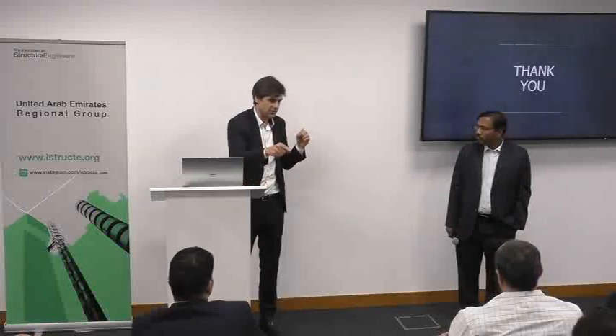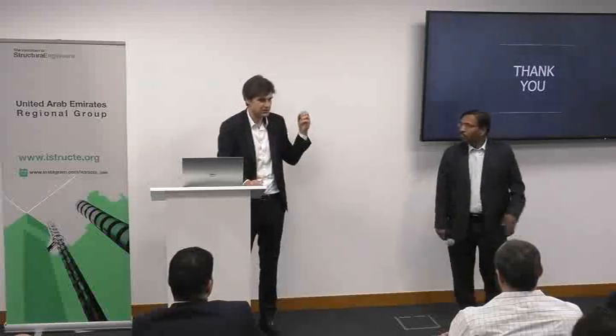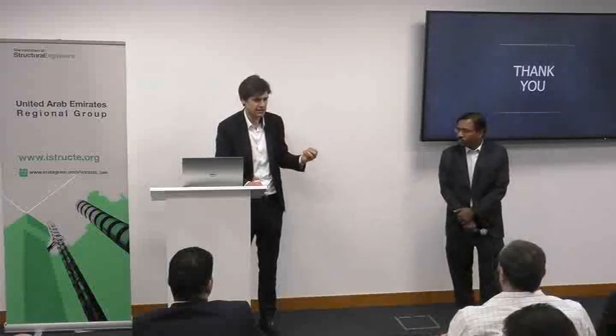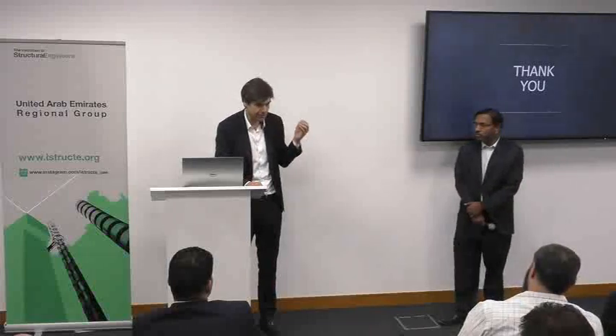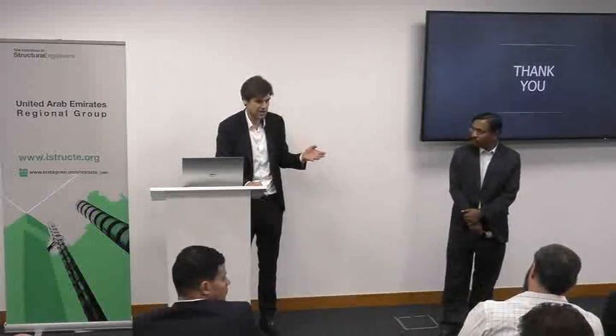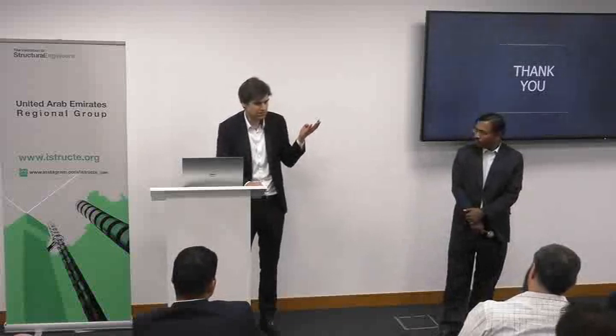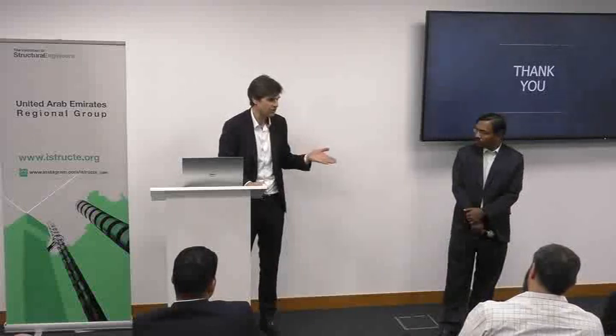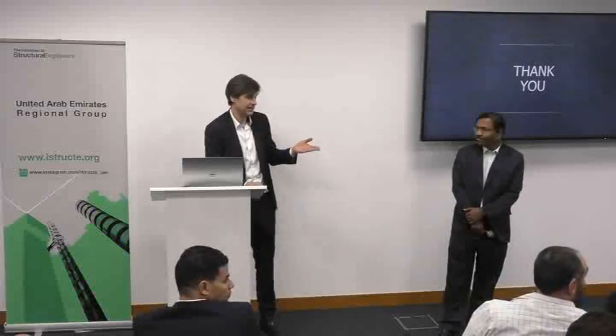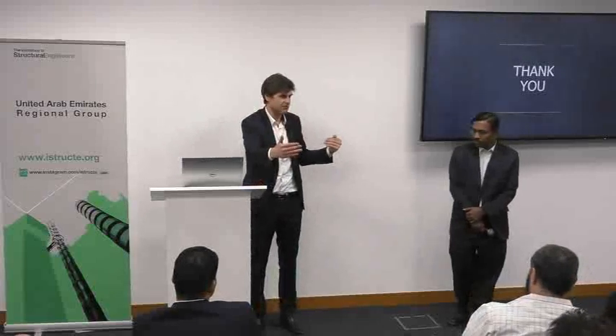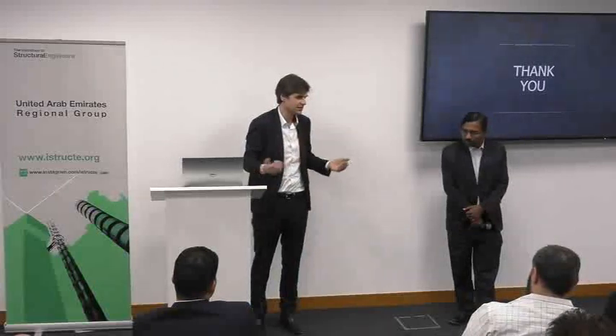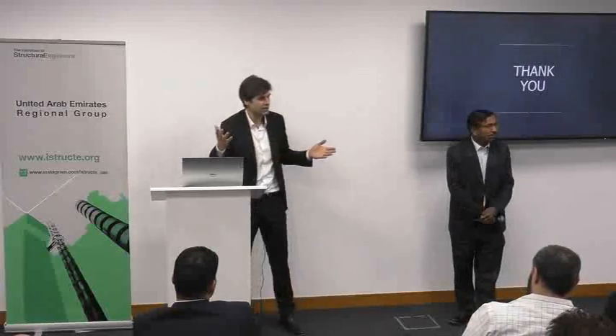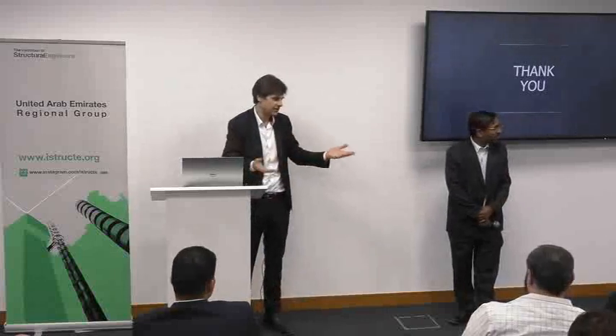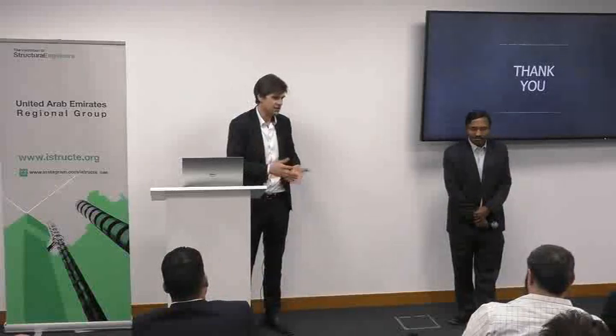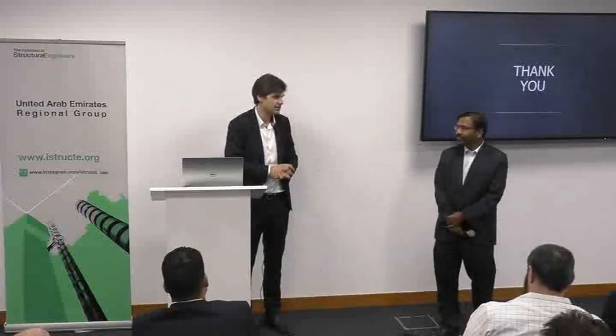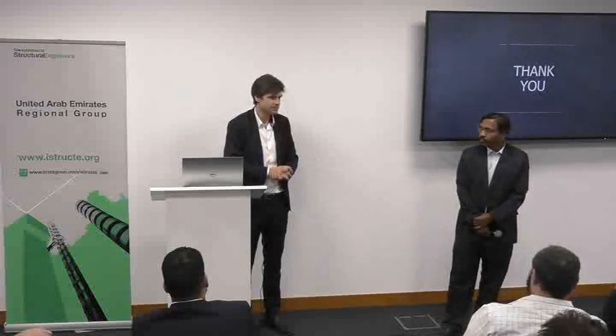Then, if I go a step beyond your question, what happens with higher stress variation? We made a test one day in VSL with 250 MPa stress variation, 10 million cycles, and we passed it. So is this 200 MPa stress cycle a limit? The response is no. It's not a physical limit. It's just a position where designers believe they have enough room for design. If they feel they don't have enough room, we can go beyond, but then we have to qualify this. We have had a test with 10 million cycles, 250 MPa on the strand system, at 619 in Vienna, a positive test, twice.